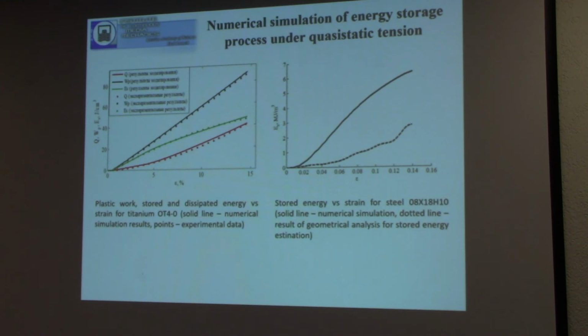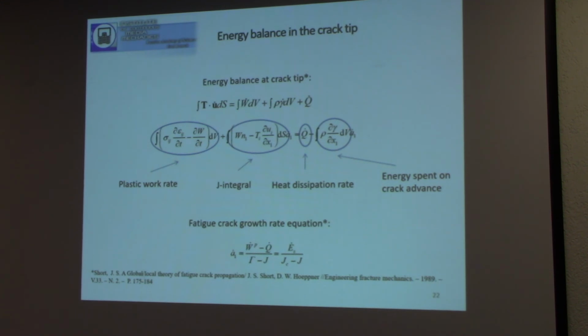It's our result. This was presented a few minutes ago. We can measure the stored, dissipated, and plastic work, and we compare the experimental results, and finally, we can use the same model for simulation of crack propagation based on the energy-based approach. For example, if we consider the energy balance at the crack tip, following, for example, Chudnovsky, we can write a very beautiful, from my point of view, equation which connects fatigue crack rate and practically the stored energy rate. And here you can see the damage energy and the J integral in a very unusual position under the line. And we can use this equation and we can try to simulate the stored energy for crack propagation.